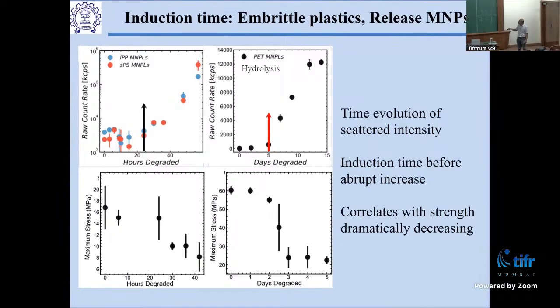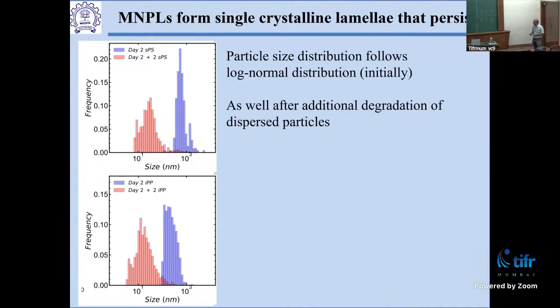This is also true for PET using a different chemistry, hydrolysis, to break it up. There is an induction time and then it takes off. And it looks like this induction time correlates with the time taken for the material to become brittle. What I'm plotting here is a stress strain plot, where I'm taking the maximum stress that gives me the strength of the material. So this is the strength of the material, and as the strength of the material decreases is when I see this induction time in the formation of these microplastics. So, the induction time really comes from the point at which these films become so brittle that they start falling apart, and it correlates with the strength decreasing dramatically in this system.